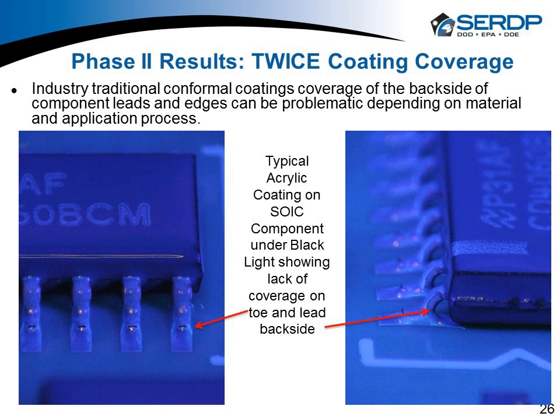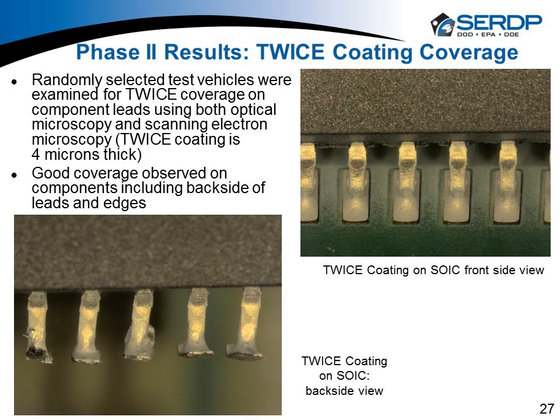So what we wanted to look at is, well, how do the TWICE coatings go down? And the picture here to the right, this is looking at the SOIC soldered down, and hopefully it shows up well, but there's kind of a ghosty, gray, milky look. That is the actual TWICE coating. One of the advantages TWICE has over conventional coatings is it's very, very thin. It's angstrom thin. And so physics, where it says on a sharp edge, a coating is going to roll off that and not wet, it's much more in play than with thin coatings that tend to stick and stay put on sharp edges compared to conventional.